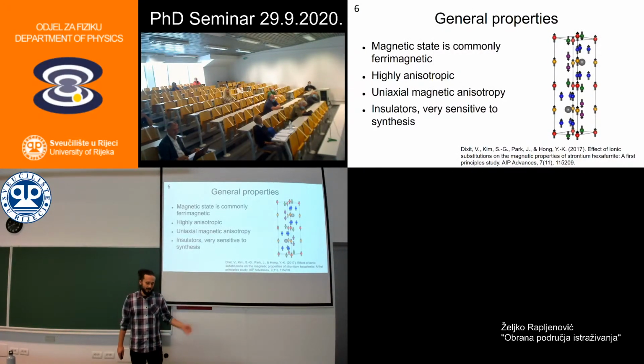So we saw an example of the magnetoelectric effect, but this is somewhat of an exotic phase. Usually at room temperature they are ferrimagnets. Here is a picture of an M-type hexaferrite with its ferrimagnetic structure, where all of these colored spheres, not the gray ones, are different coordinations of iron, and the arrows represent the magnetic moment at the site. We see that some of these moments point up, some point down, but the general consensus is pointing up, and this is a ferrimagnet.